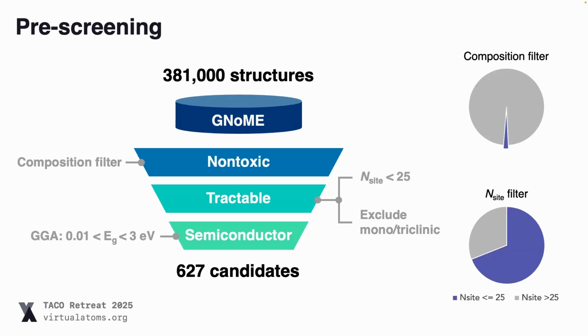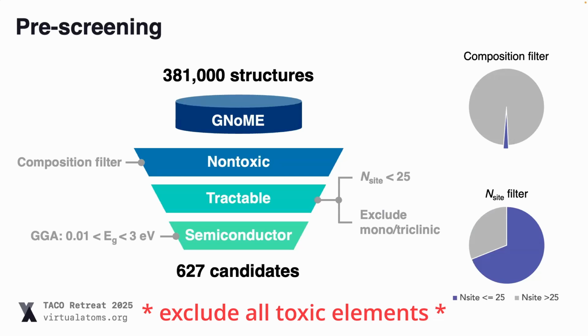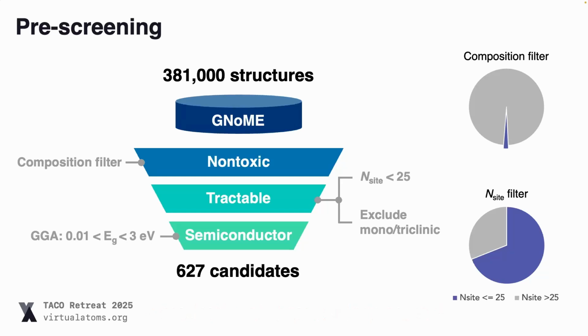So our first step was just to take this data set and do some pre-filtering. The first thing we did is exclude all toxic elements, because we're interested in a material which might be commercially relevant. If it's toxic, it makes it difficult, especially if we want to put it on a phone screen, for example. It's going to be difficult to sell that. And actually, as soon as we applied the non-toxic filter, this eliminated a huge amount of the materials. The other thing is, we wanted to run some high throughput calculations, so we wanted to make the project tractable. And so we limited ourselves to materials with less than 25 sites and excluded these very, very low symmetry structures. There might be realistic monoclinic structures in there, but there were just so many alloyed structures that we needed a very easy way to filter them out.